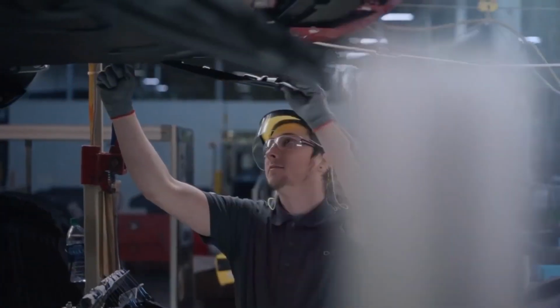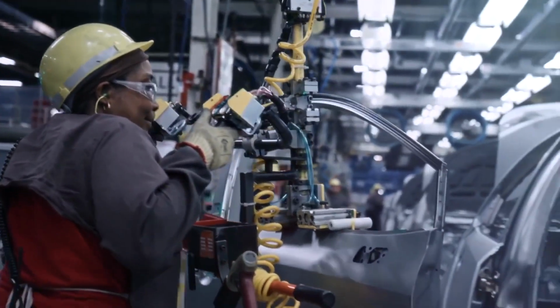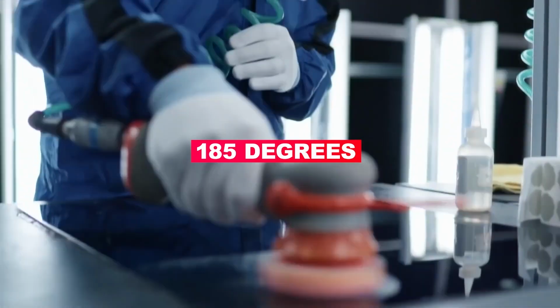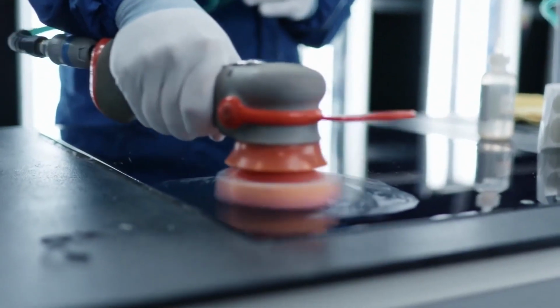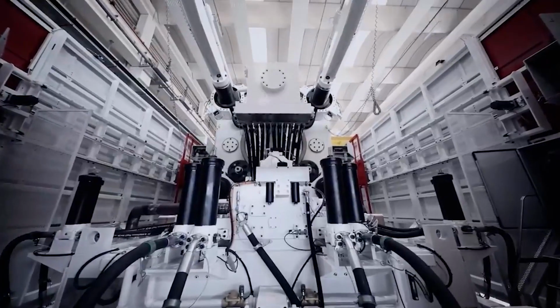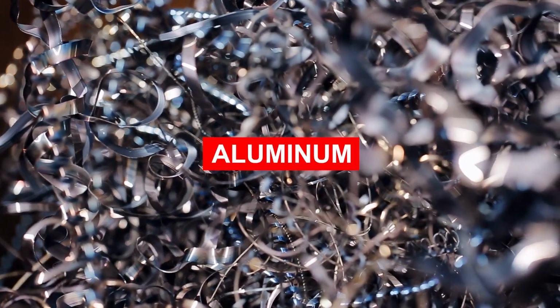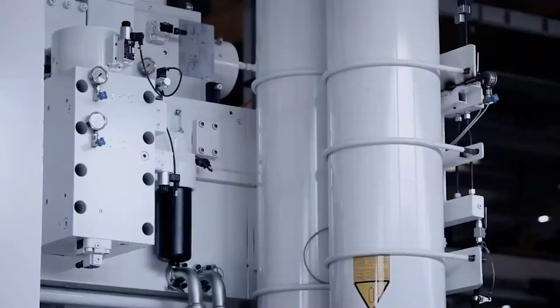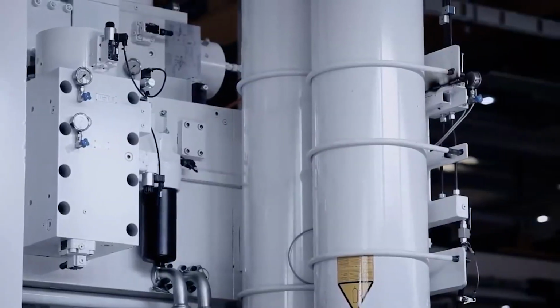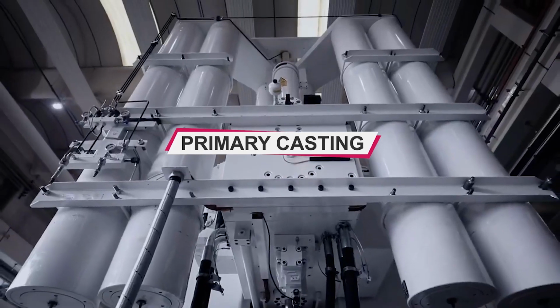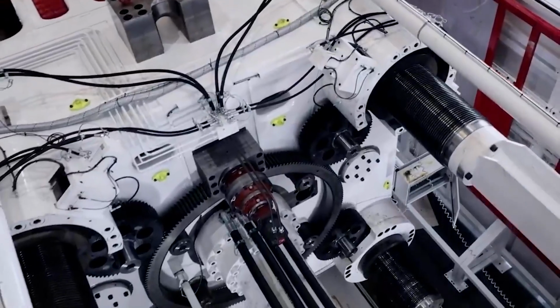Within 1 to 2 minutes of the current casting cycle, robots gently clean the open die and cool it to 185 degrees Celsius to prepare it for the following cycle. The next one will now be finished. Using a mechanical trim press, each raw casting should be roughly trimmed to the required proportions. The aluminum scrap is recycled and reinserted into the furnace using a scrap metal shredder. The primary casting is next examined using an X-ray to discover whether it has any internal faults.